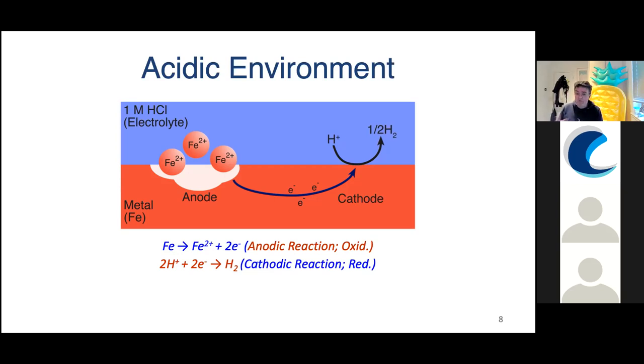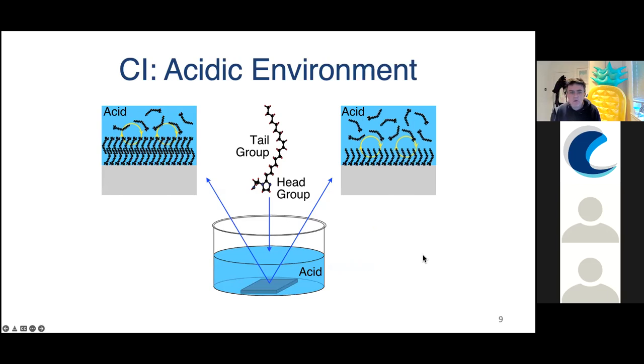And the inhibitor needs to interfere with one or more of these reactions, either the cathodic or the anodic reaction, or both, which would be a mixed type inhibitor. So this slide just shows you a bit more detail of what's going on, or what we think is going on in an acidic environment. So here's a typical sort of molecule we might add as a corrosion inhibitor in an acidic environment. It's an organic molecule, and it has a so-called head group that's interacting with the surface.